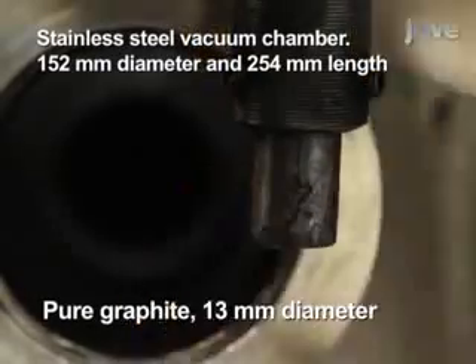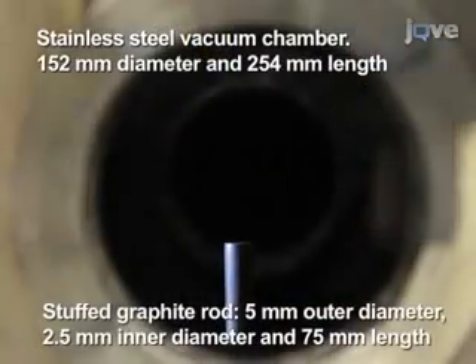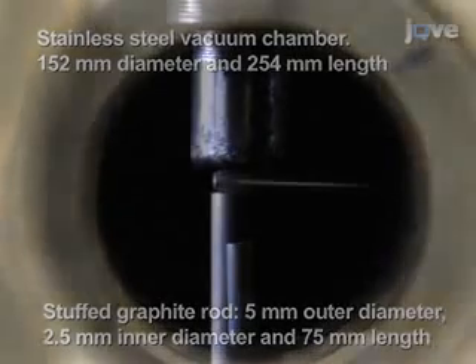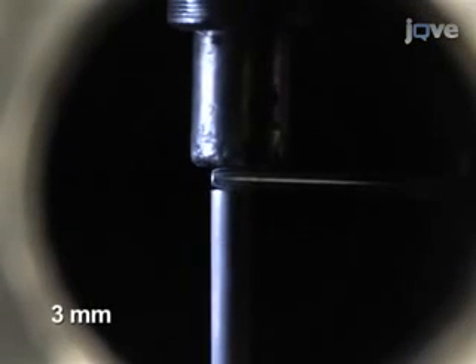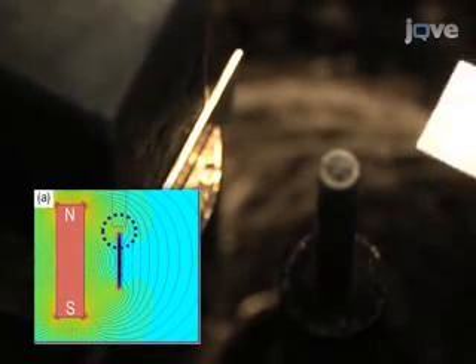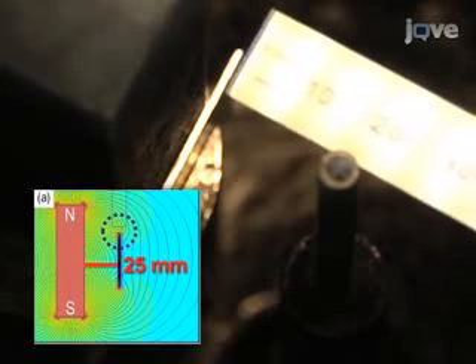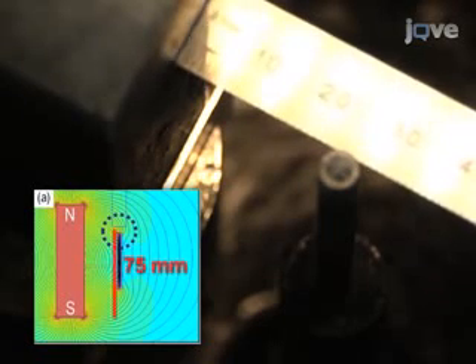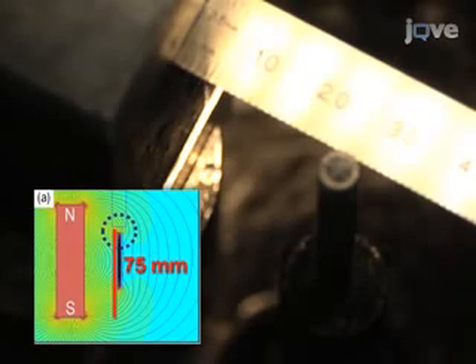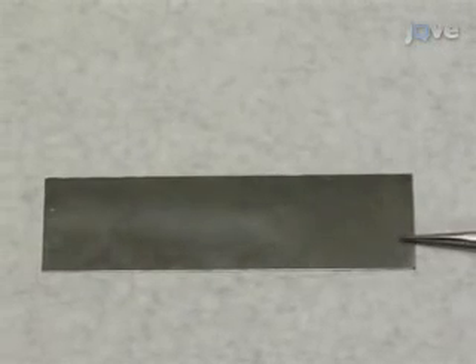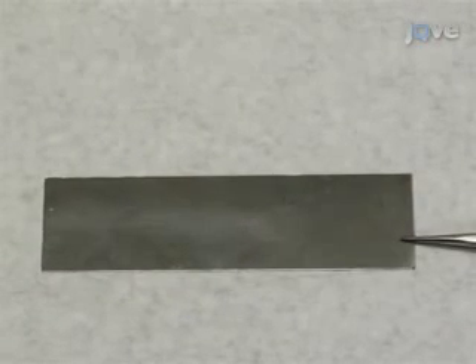Install a cathode rod and the stuffed anode rod inside the cylindrical chamber. Adjust the gap distance between the cathode and anode to about 3 millimeters. To set up the substrate, place a cuboid permanent magnet inside the chamber about 25 millimeters away from the interelectrode axis. In this configuration, the interelectrode gap is set at a distance of about 75 millimeters from the bottom of the permanent magnet. Cut a 0.3 mm thickness molybdenum sheet into a 25 mm by 100 mm rectangle.